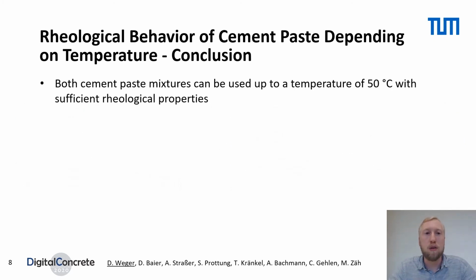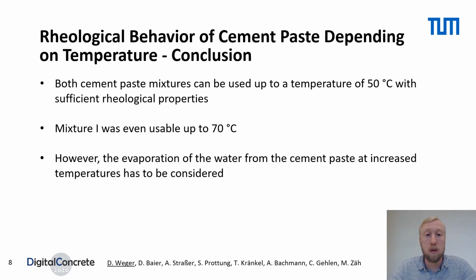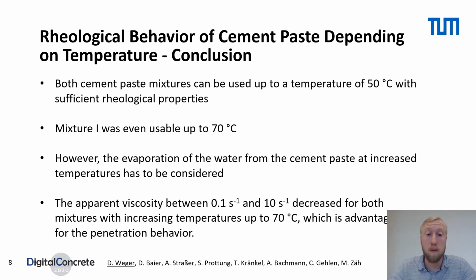Now let's have a short conclusion of the results of the rheological measurements. So both cement paste mixtures can be used up to a temperature of 50 degrees Celsius with sufficient rheological properties, and mixture 1 was even usable up to 70 degrees Celsius. However, the evaporation of the water from the cement paste at increased temperatures has to be considered in further investigations. The apparent viscosity between a shear rate of 0.1 and 10 decreased for both mixtures with increasing temperatures up to 70 degrees Celsius, which is advantageous for the penetration behavior.